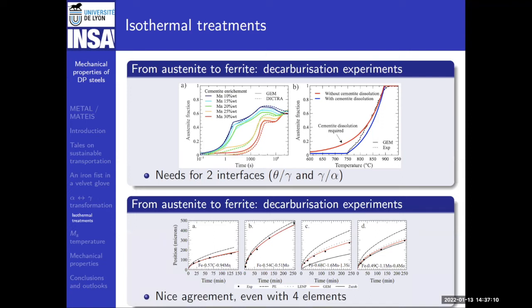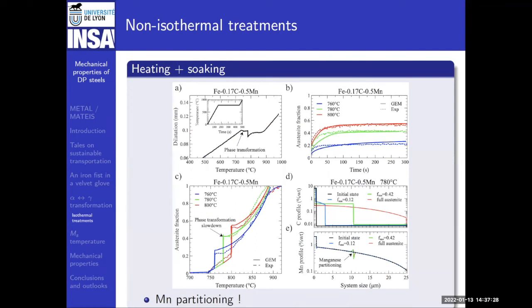And the model was also checked on other systems, many systems where we studied the transformation kinetics for very famous experiments performed by other researchers. Okay? So we also did some more complex treatment, which is more like the industrial one, where you have heating and then isothermal. And we see that during heating and isothermal, the transformation stops and continues. So it's interesting to see what is happening during heating and during the isothermal treatment. So you see that during heating there is transformation, and then it continues while you are at the same temperature, and then eventually when you heat up again, it starts again to transform. And what is important is that during this isothermal process here, the transformation continues and we have manganese partitioning. That's very important for the kinetics of the transformation.